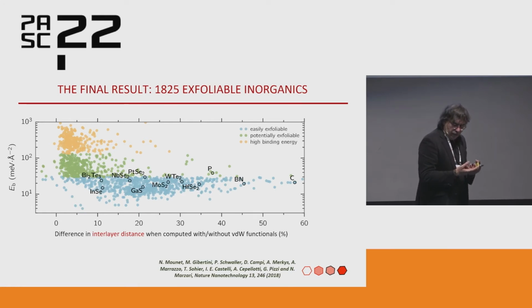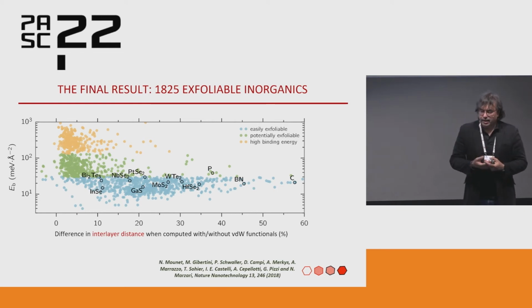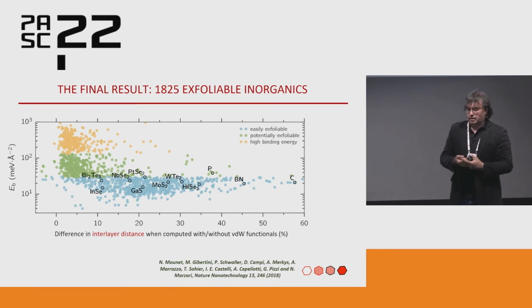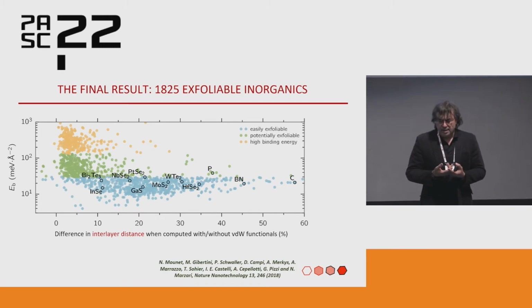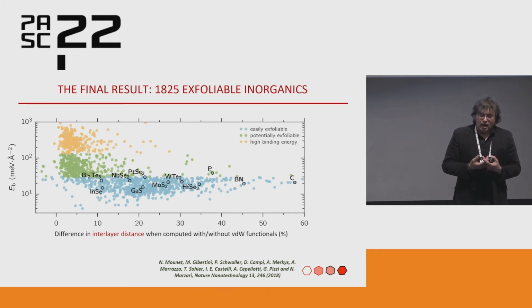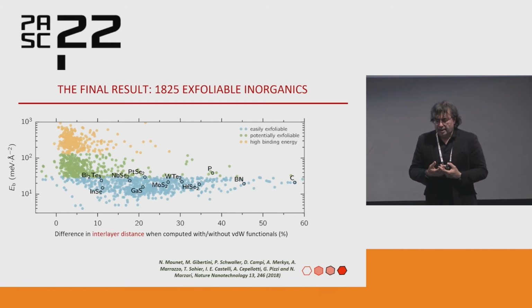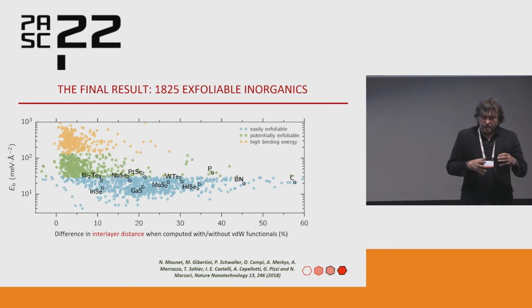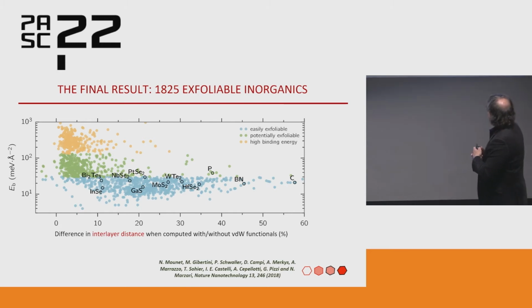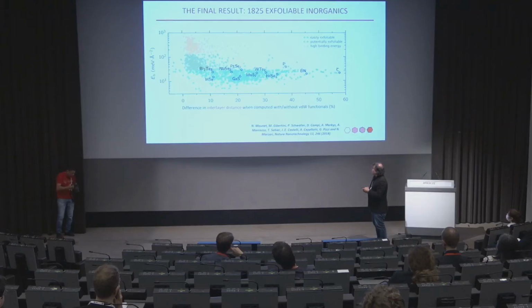So this was the result of our first effort. And this is actually the paper for which we were kindly awarded the PRACE HPC Excellence Award. So we studied with explicit computational quantum mechanics calculations 5,619 materials. We did roughly 500,000 calculations, and the results are here. Every point, this is a bit sparsified, is basically one of those 5,000 materials. And you can roughly cluster them into yellow, green, and blue, according to their binding energies. And for reference, this is graphite. So 20 millielectron volt per angstrom squared is the binding energy of graphene. This is what Geim and Novoselov exfoliated. So on the x-axis, on the y-axis, we have the binding energies.